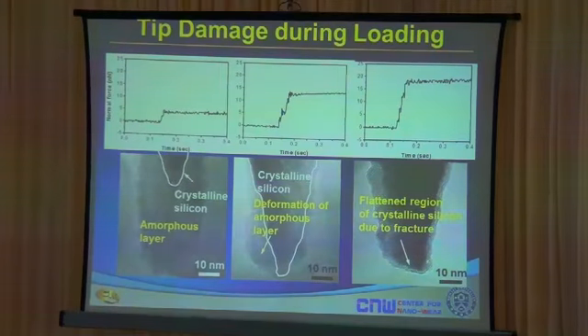Another thing that we should be aware of is tip damage during approach. If you have an AFM tip and you're trying to approach your specimen, but you do it at the wrong rate, you will damage your tip in that approach process. What you're looking at here is the normal force in nanonewtons, up to 5 nanonewtons, against the time of loading. In this very short time of low force loading, your tip shape remains intact. In other words, you do not damage it. However, if you increase the rate at which you approach the surface, at a very high load of 15 nanonewtons, you can see that you've severely damaged your tip just by approaching the surface. So this is another thing that we have to be aware of when we're using the AFM.